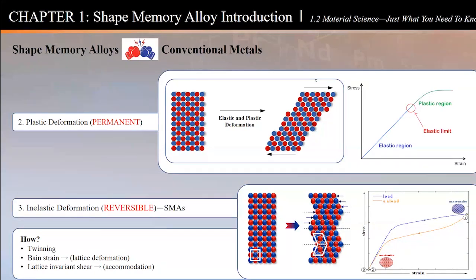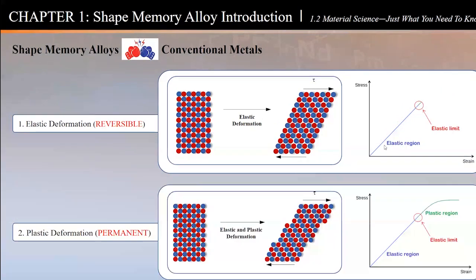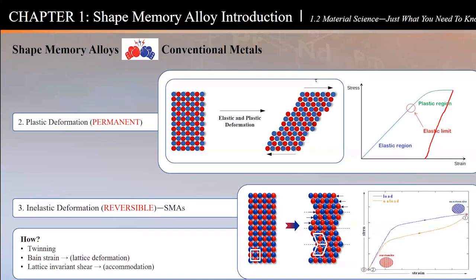What's the result here? If you look at that deformation, if I go just a little bit, it looks like elastic, just like my elastic model over here, a straight line. Now, if I go past the elastic region, it looks like plastic deformation right here. The only difference is, if I take this sample and unload it, it comes down like this. But if I stop here and I unload my sample, I take the load out, it actually recovers everything. That's the recovery. So almost like a rubber band, but it's a piece of metal. This recovery could be in the order of 10 times more than the elastic portion of your conventional metal.